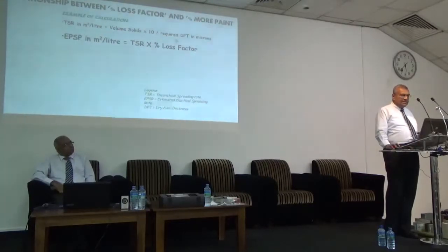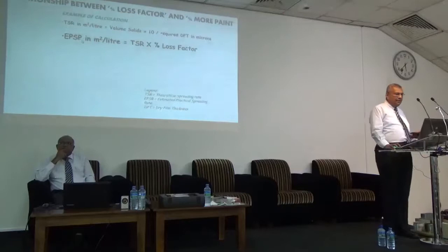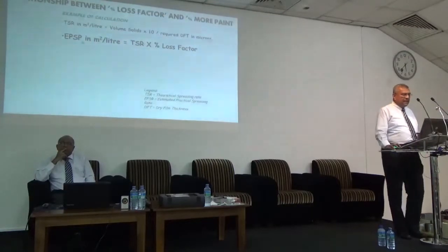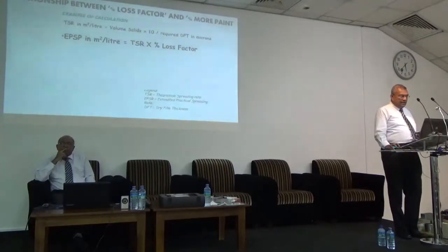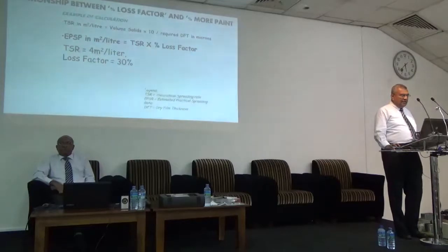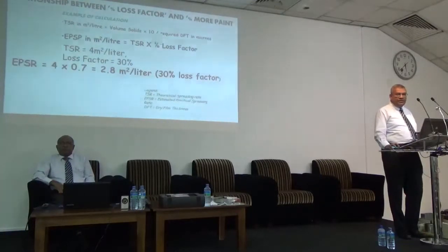So now we have the TSR, we know the TSR, now we go for the PSR, practical spreading rate. Estimate the practical spreading rate. Okay. And then if TSR is 4 square meter per liter, the loss factor is 30%, then we know 2.8 square meter per liter will be the practical spreading rate.